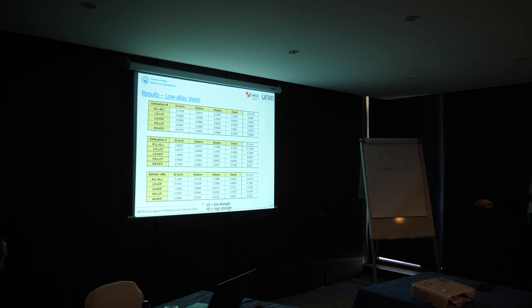For certain methods, I will point your attention to some cases. For example, the hardness estimation method has a very low percentage of data for high-strength materials in the low cycle fatigue regime — only 20% of data points fall within the scatter band of three. There is also additional information for a scatter band of two. If we had not done the detailed analysis, all we would have is the very general average information that almost 85% of data falls within the scatter band. You could possibly make a very large error if you implemented these estimation methods for a subgroup of high-strength materials in the low cycle fatigue regime. Similar information can be extracted for other subgroups as well.